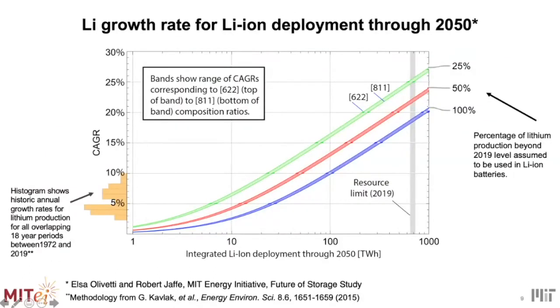Well, the question of what lithium ion can do comes up over and over again. And I want to show you just two slides from some work that is ongoing, led by Elsa Olivetti and Bob Jaffe, colleagues of mine here at MIT who are working on this future of storage study. Okay. And the resource limitations are always in our minds, and so lithium is one of them for sure. Okay. And what this plot shows you is, on the horizontal axis, on the log scale, how much storage we might need. And so you see our 100 terawatt hours there. And compared to that, the resource limit is actually higher. Right? So there is actually enough lithium available.